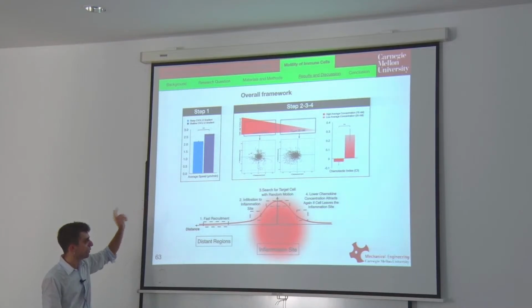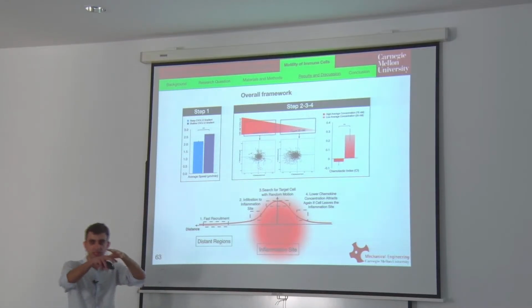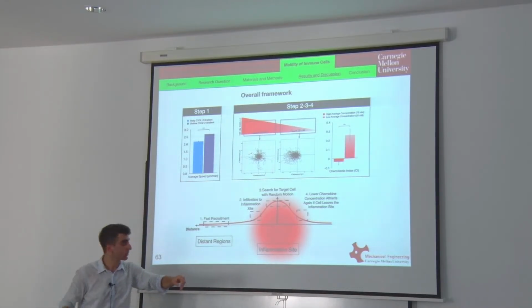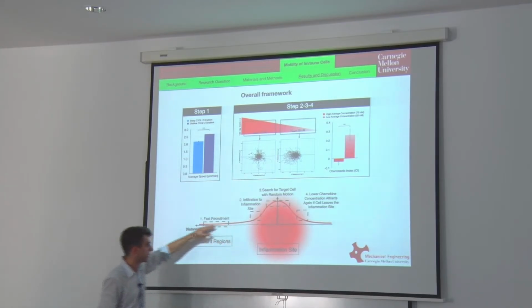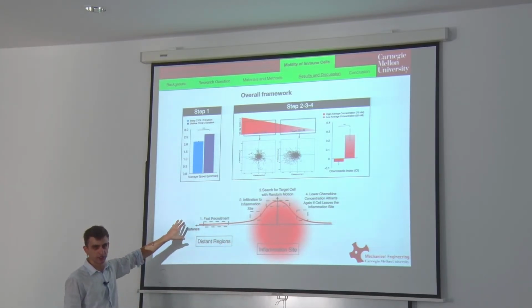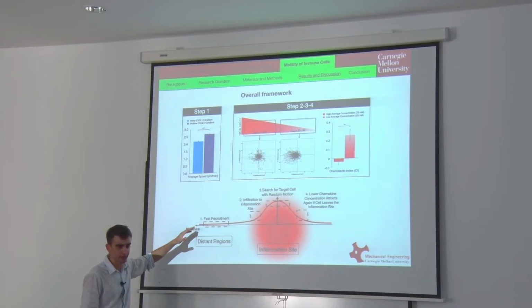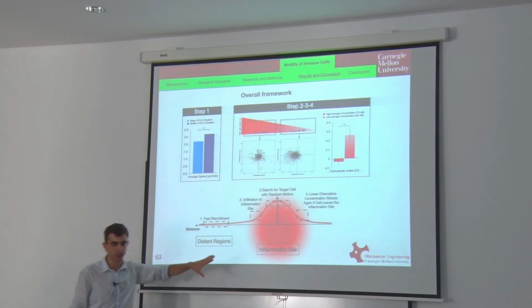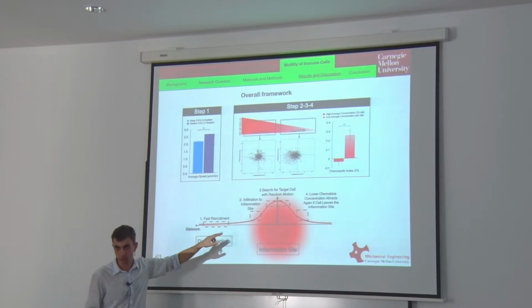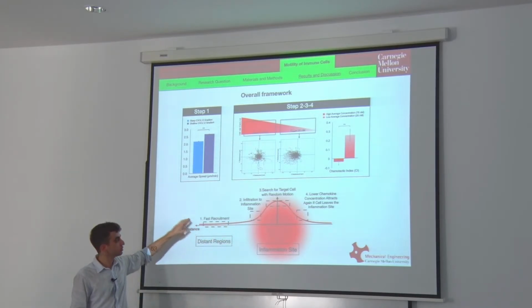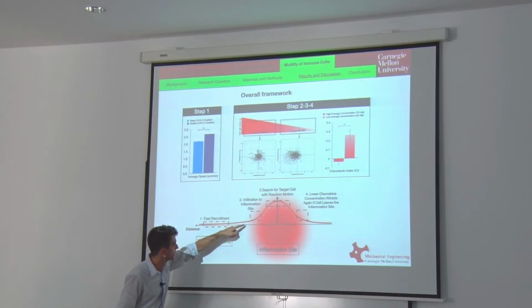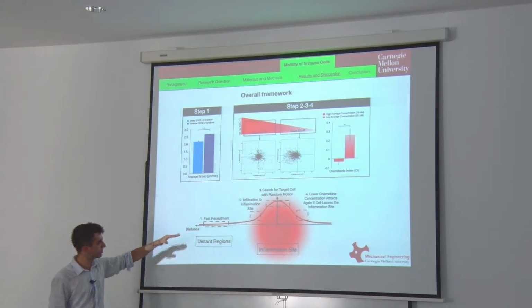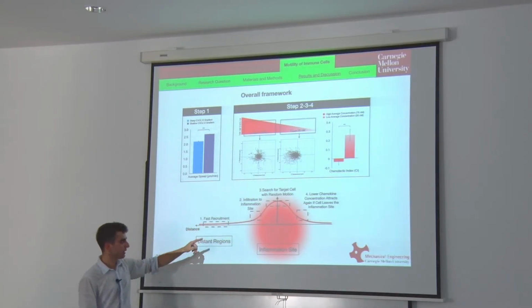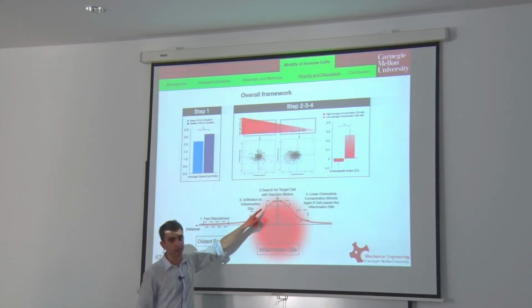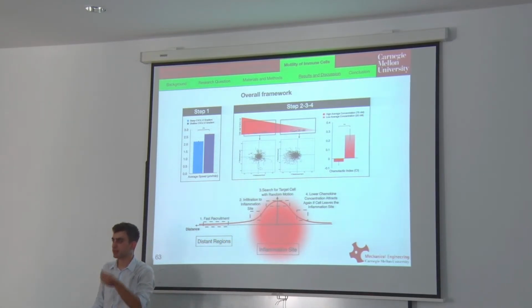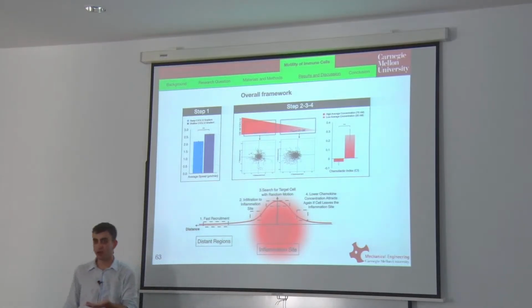So when there is an inflammation, chemokines are diffused in 3D, which creates this parabolic profile. And in the regions that are far away, that are distant from the inflammation site, the chemokine gradient is very shallow. And this is where the immune cells are. So they are quickly recruited to the inflammation site because the chemokine gradient is shallow. And they enter the inflammation site, and in the inflammation site, there's a gradient, but the average chemokine concentration is high, so they move randomly.